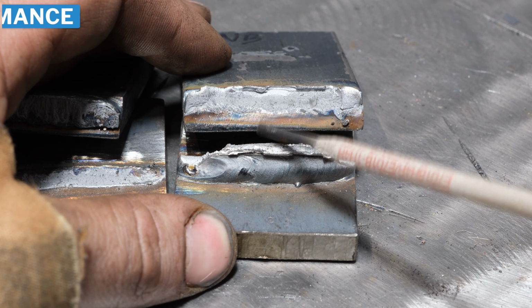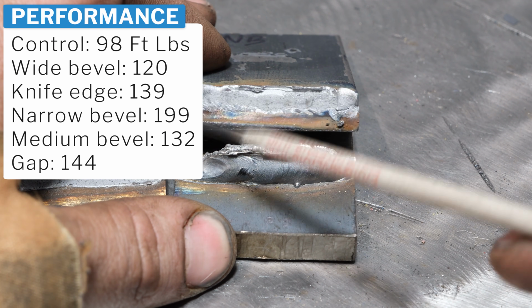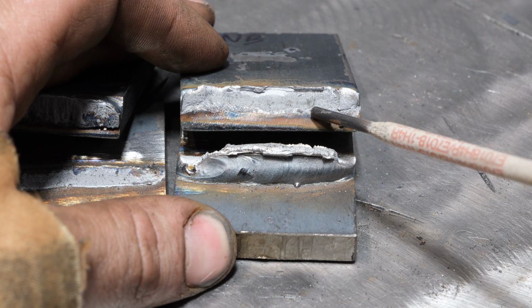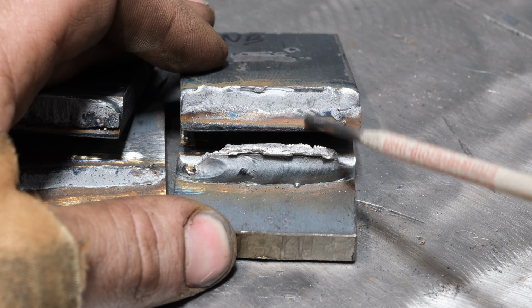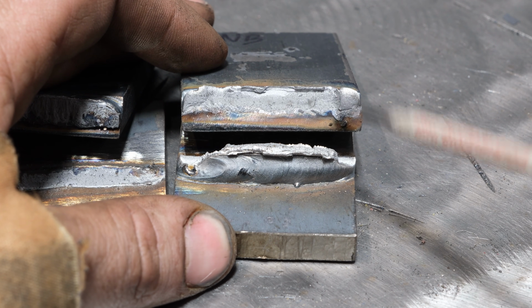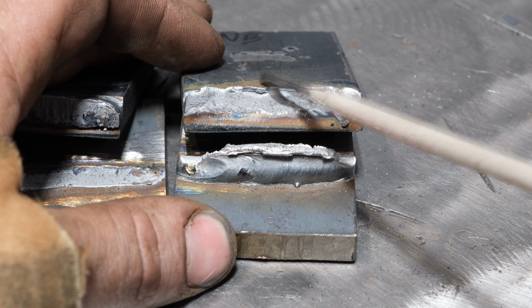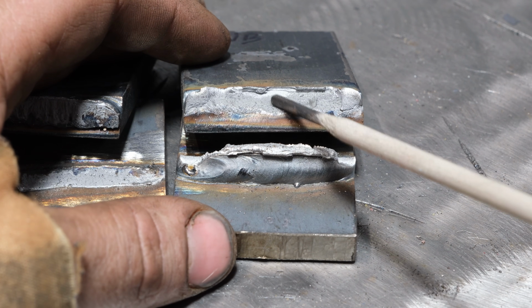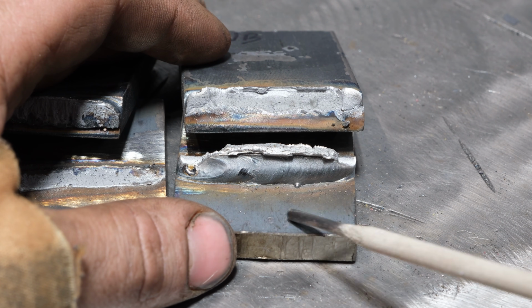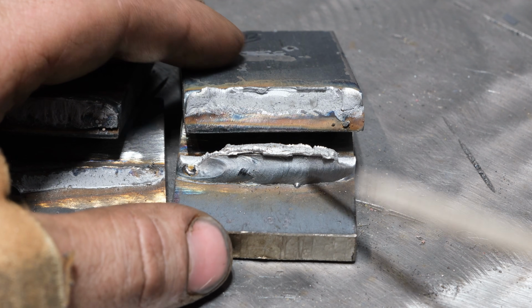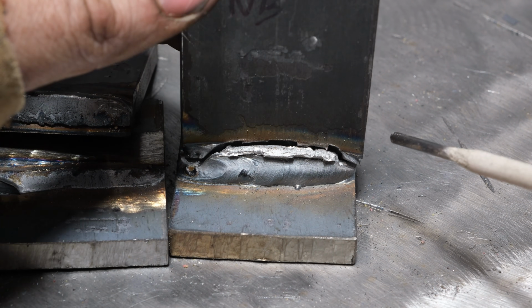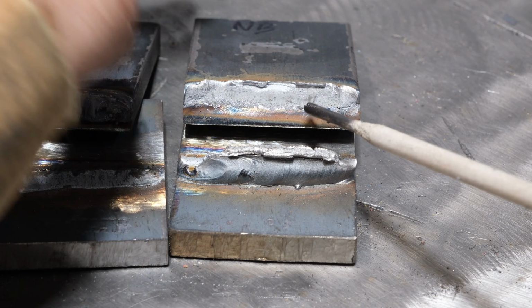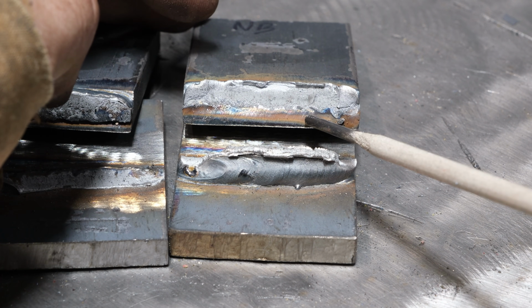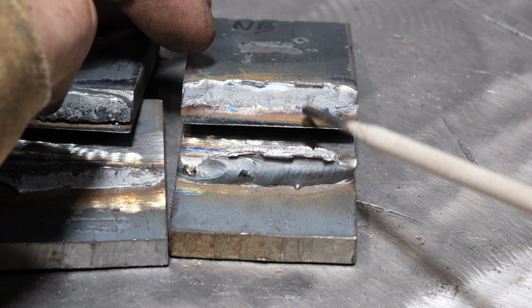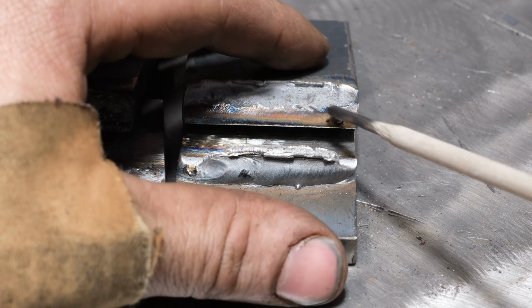Now the narrow bevel, if you look right here, there's a completely untouched half of that bevel because simply it's not going to melt further in than what the wire can get through the molten puddle at. So completely untouched. It did bite really good into the plate here, as well as you can see it broke off of this plate more so than here. It likely bit very well into here, and this posted very good numbers as well. So for the sake of testing purposes, this performed better than I would have thought. However, once again, putting a full-length bevel on it like this is not going to be utilized without running a wide gap between the plates plus the bevel. So interesting there. Let's move over to the knife edge and the gap.